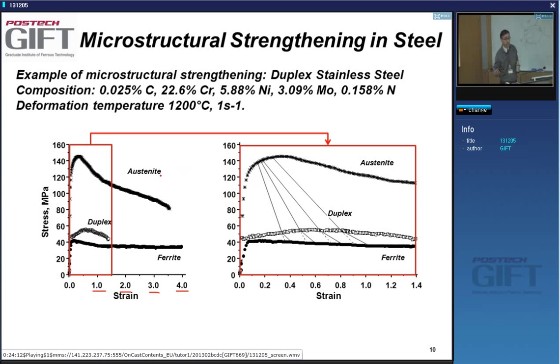This was analyzed by one of my graduate students. He found the distribution of strain and stress during the test. At a given point in the duplex steel, you have a certain stress and strain in the austenite phase and a different stress and strain in the ferrite phase. Again, you have what is called stress and strain partitioning.